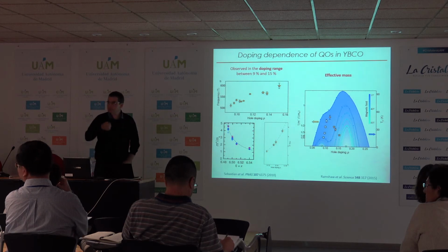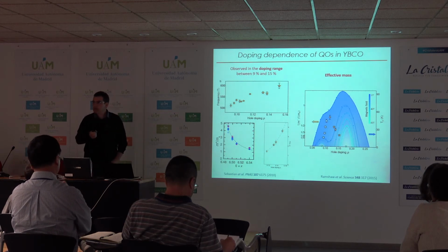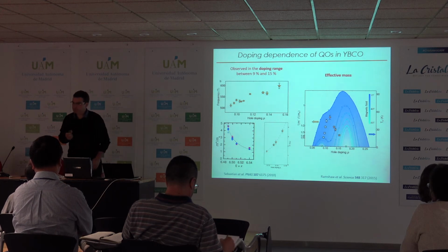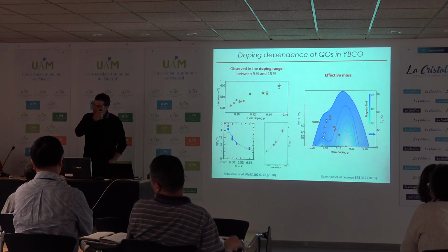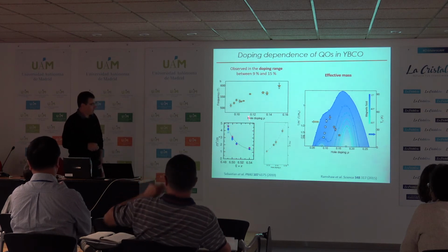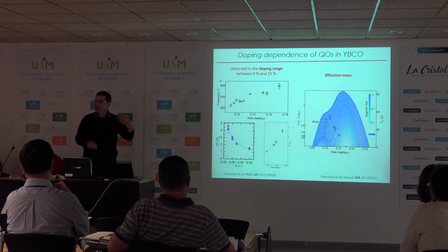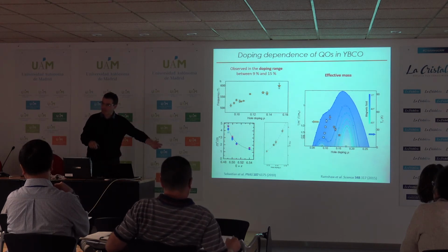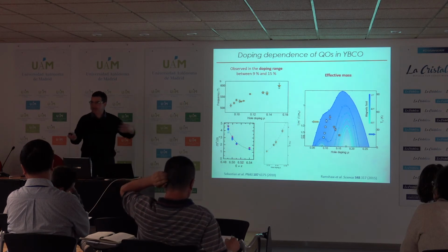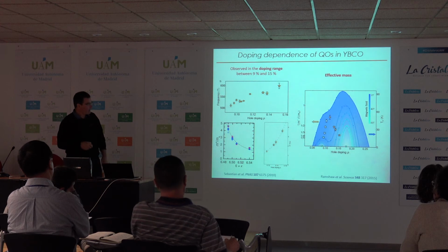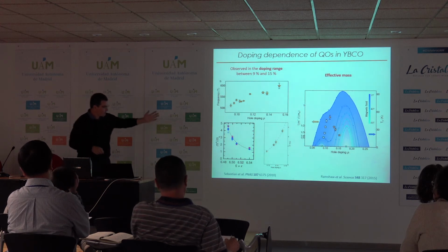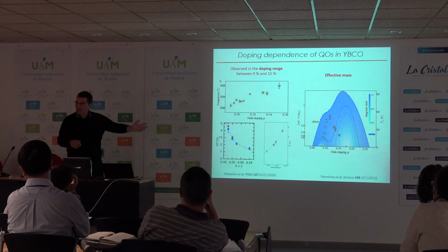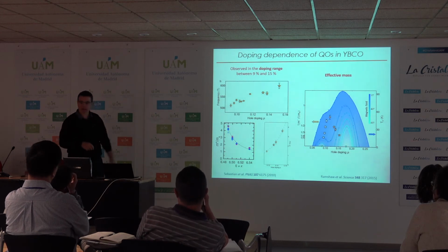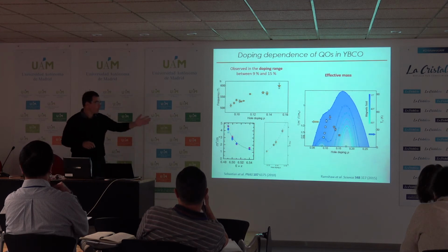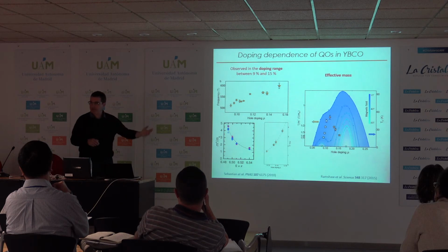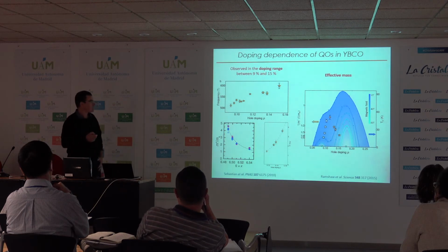Cyril, you had said that on the overdoped side you already saw a mass enhancement of 5. Yes. But here you're thinking 5 is like a divergence. I'm just wondering. It's a divergence. What you see is a strong increase, which is reminiscent of what happens when you arrive close to a continuous critical point. Okay, that's the message basically that I will discuss after. But I agree that there is an increase by a factor of 2 of the effective mass when you approach such a point. Unfortunately, you cannot measure quantum oscillations about the doping because critical fields will become too important.